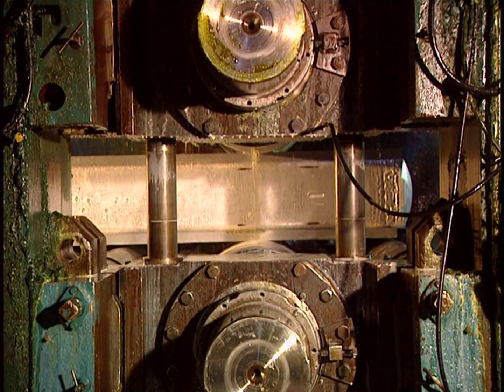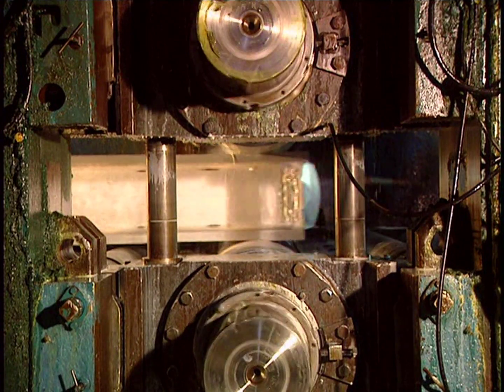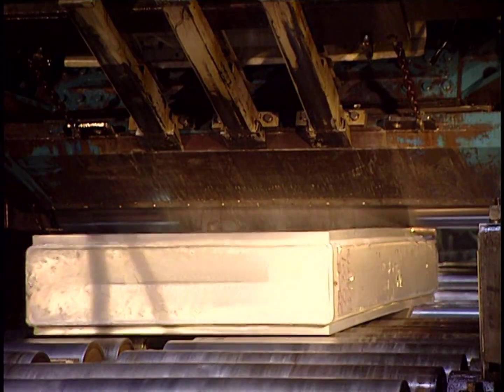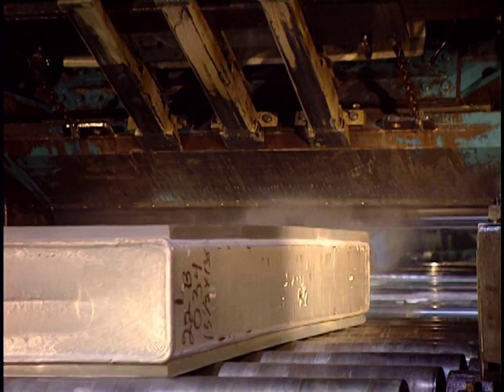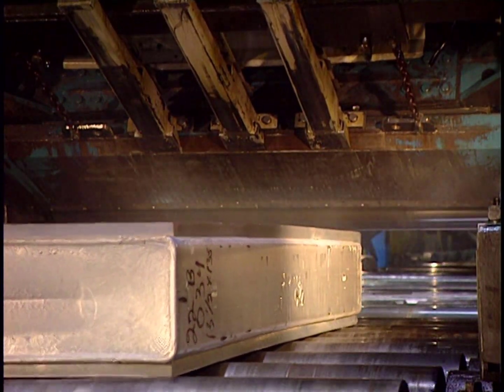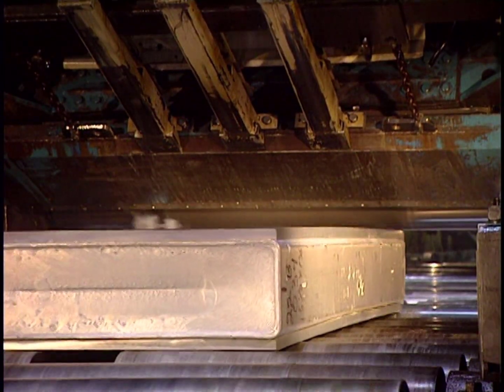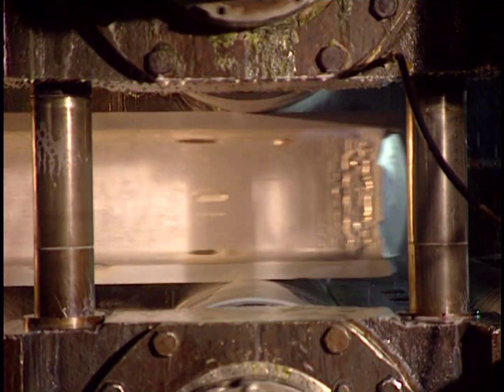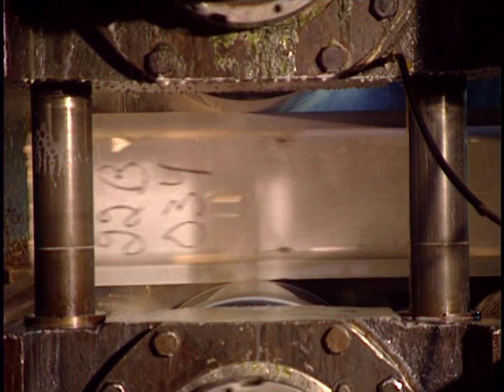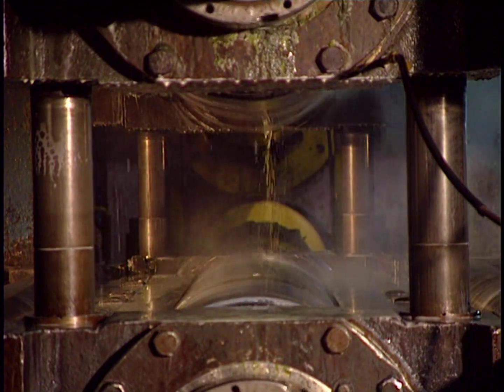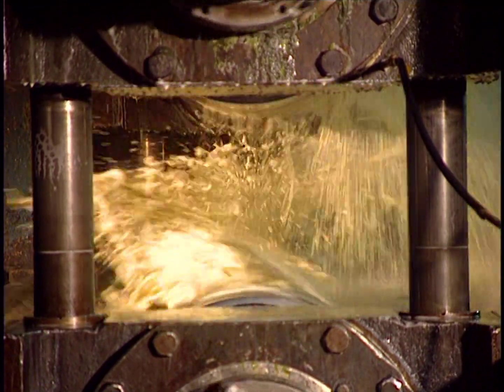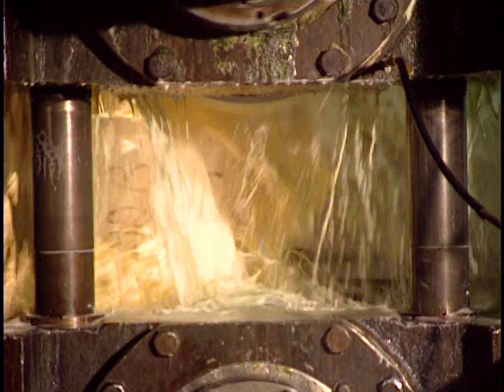Temperatures in the rollers are between 850 and 1,000 degrees Fahrenheit. Pressure on the ingot is continually verified by a technician. If the pressure is too great, the technician will lower it. The heat is so high that the ingot risks sticking to the mill's roller. To prevent this, everything is cooled with a liquid that's 95% water and 5% oil.